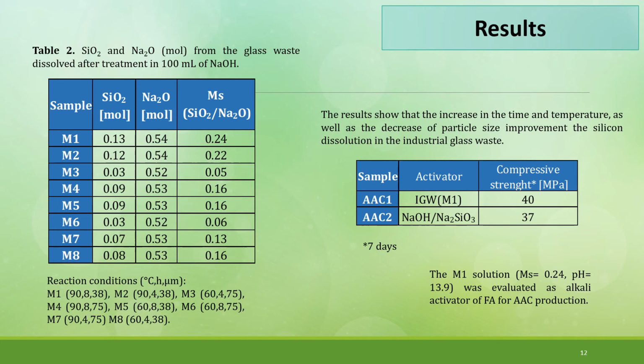In this table we can see the amount of silicon oxide and sodium oxide that was dissolved in the activating solution, and it is observed that the sample with the highest amount of dissolved silicon was number 1, which was prepared at 90 degrees Celsius for 8 hours, and the glass with a particle size of 38 microns. The results show that the increase in time and temperature, as well as the decrease of particle size, improve the silicon dissolution in the industrial glass waste.